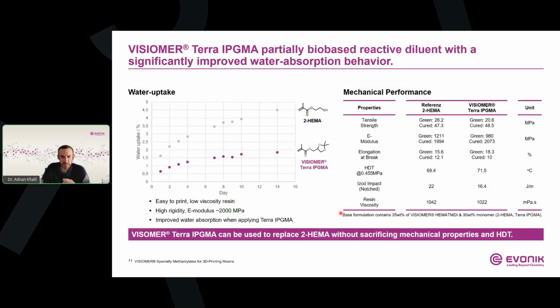To investigate this, we benchmarked the Terra IPGMA against the commonly used hydroxy-functional methacrylates in a representative photopolymer formulation, and we found that the Terra IPGMA can be readily incorporated into a typical photopolymer resin formulation while maintaining good key mechanical properties that are required for the 3D printing application.